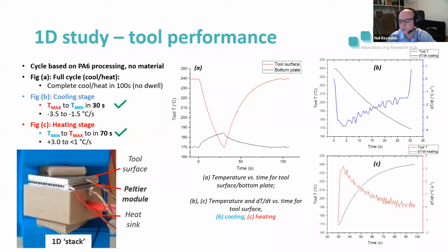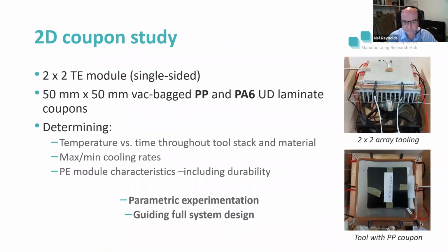The efficiency drops as the temperature differential drops. It goes down to about 1 degree a second cooling and heating. But the sort of take-home message from this is we can do, as I said, the whole cycle in about 100 seconds. So if you were to include a dwell in there, you could probably do the whole thing in about 3 minutes. Next slide.